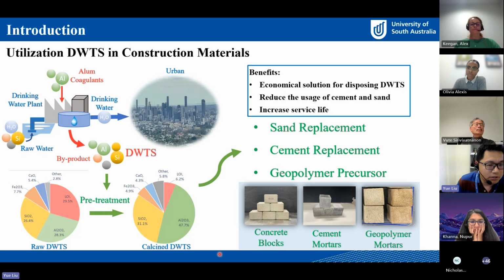After pre-treatment, the aluminum and silica content in sludge occupies around 80% of the total mass. These results indicate its pozzolanic reaction potential when used as cement replacement. Because for cement, when it touches water, it will generate some C-S-H gel to bind fine aggregate and coarse aggregate together to make the concrete hard.